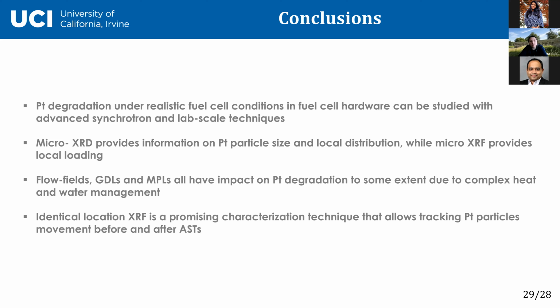And identical location XRF is indeed a promising characterization technique that we'll hopefully see deployed more by other groups. We already adopted it for electrolyzers. So we do similar degradation studies on iridium oxide catalyst and try to map it beginning of life, end of life.